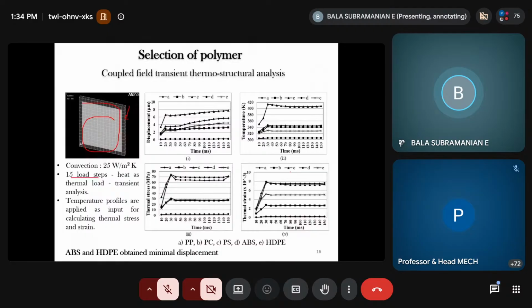We want to work with reference to around 200 degrees C, because our team member was asking about the temperature range the heater can handle, up to 300 degrees. So we want to understand almost the 200-degree range particles, and HDPE, of course, gave a minimal displacement. That factor, we have selected the HDPE for our further work.